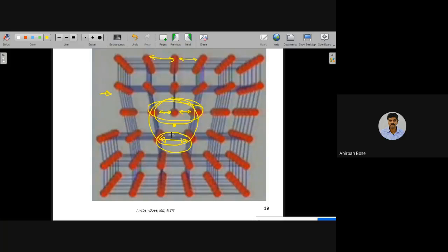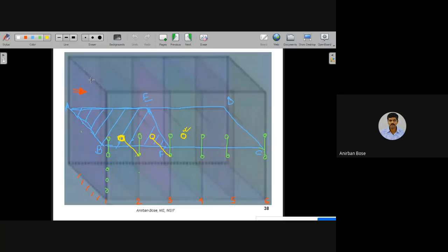Now, if you go to the previous slide, you can understand this is the line around which you observe the disturbance. Just above it, you will find compression. Just below it, you will find tension, right? So EF is the line around which you are observing this imperfection.